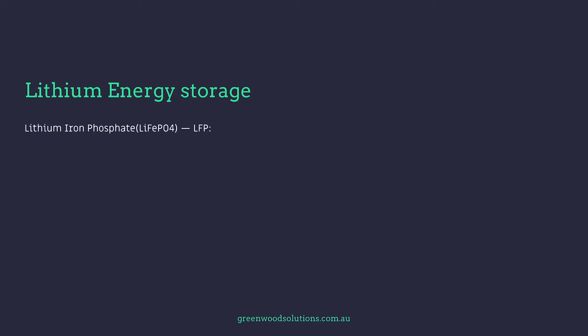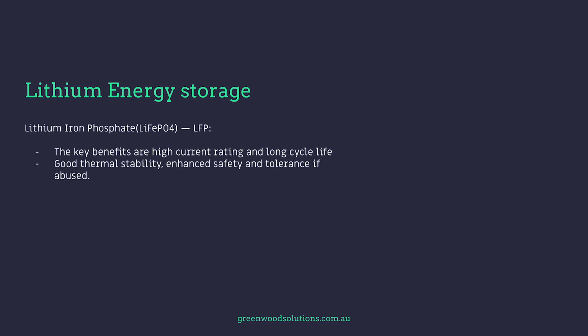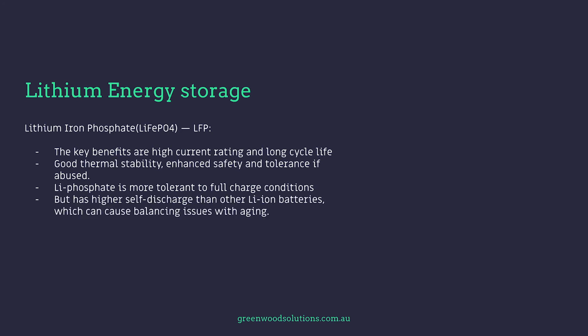Lithium iron phosphate, LFP. The key benefits of lithium iron phosphate are high current rating and long cycle life, good thermal stability, enhanced safety and tolerance if abused. And lithium iron phosphate is more tolerant to full charge conditions. But it has a higher self-discharge than other lithium batteries, which can cause balancing issues with aging.